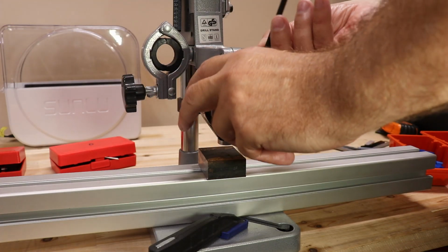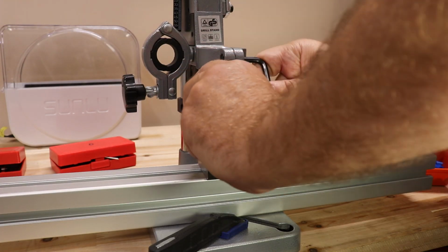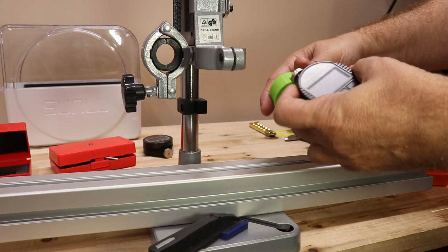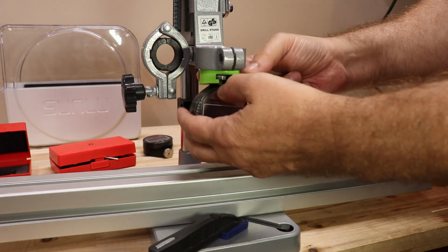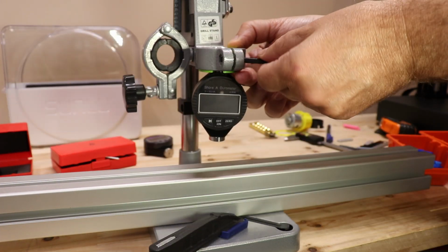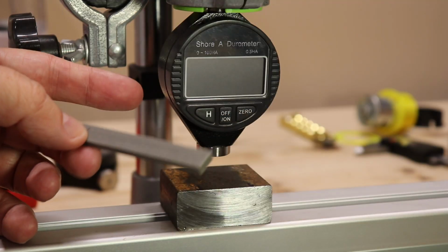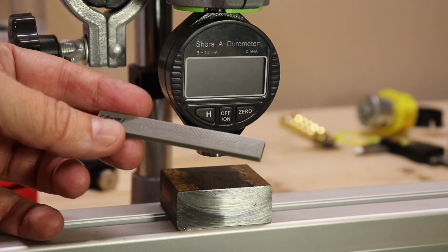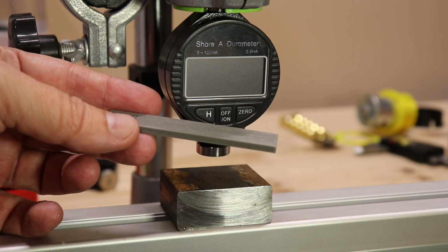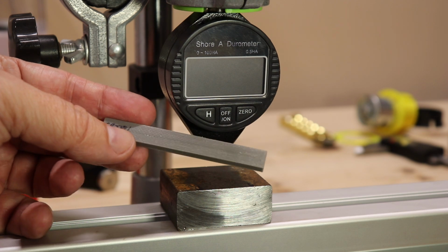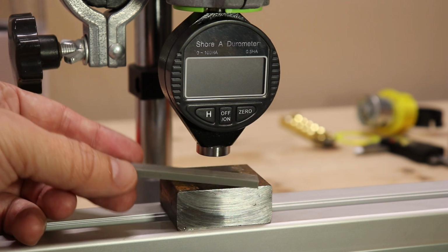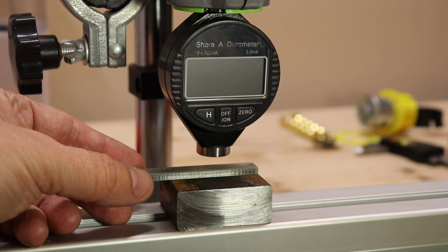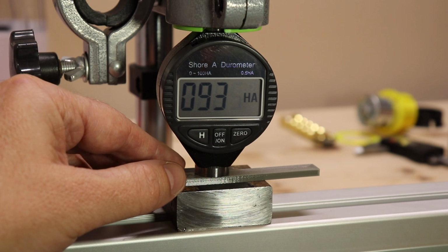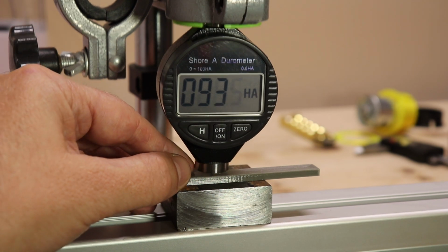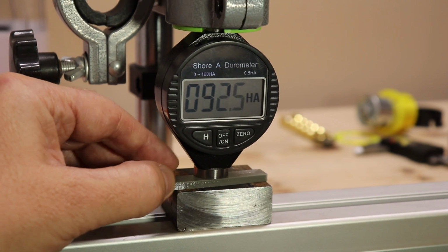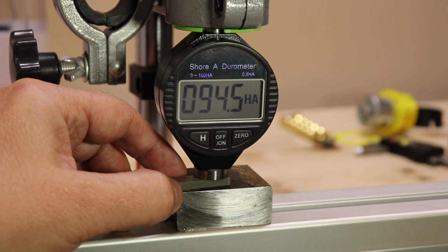And now I replace this durometer from Shore D to Shore A, and now measuring the TPU with the Shore A. From Shore D I can see some small spots from the indentor, and here theoretically we don't have that spot. So if you don't want to damage your part, probably this is the better solution. 93, 96.5, 95, 93, 92.9, and 94.5.